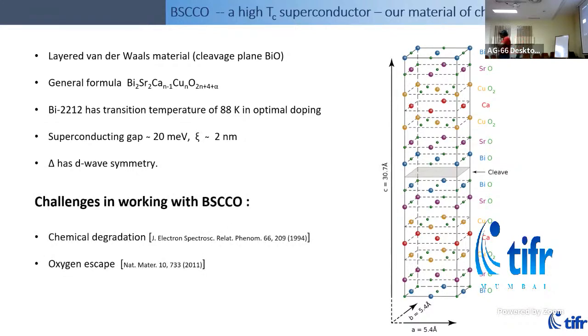For us, experimentally, one of the common problems of BSCCO, which have been known for many years, is that degradation is very rapid. So unlike graphene, where you can make a device and come back to measure it for like 6 months, a year, and nothing will happen, it is challenging to work with BSCCO because you have to make the device and cool it down below 200 Kelvin immediately, because then the chemical degradation stops. As long as it's below 200 Kelvin, you can measure for months. As long as you don't electrically kill the device, you can measure it.